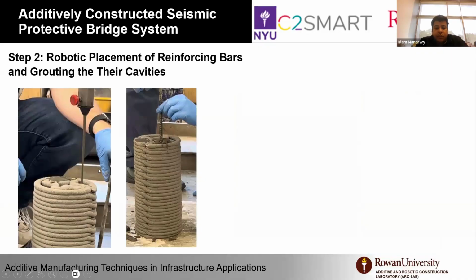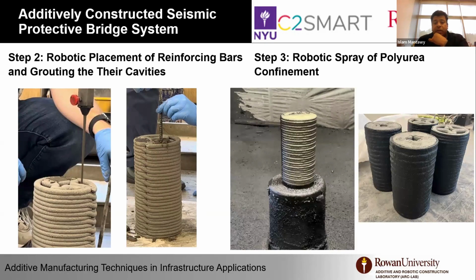You can also place reinforcement and fill it using the printer itself by changing the rheology of the material. You can do it early on, but you need to place the reinforcement first and cast or fill it later, right after printing. But for safety for ourselves, we fill it a few days after to allow the column to cure. We incorporated vertical reinforcement, however, we didn't have spirals or ties, so we studied different materials in the literature, and we found that polyurea material, which has very good water resistance and impact resistance, can be sprayed against the column and provide significant confinement that is close to what a spiral would add.